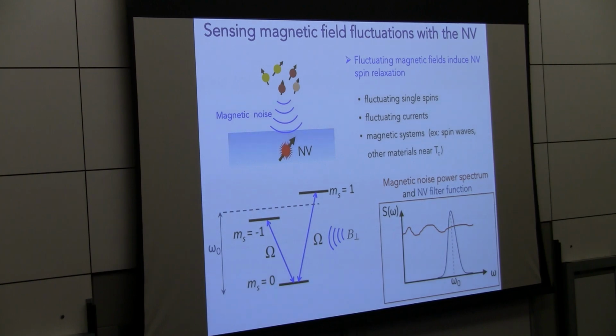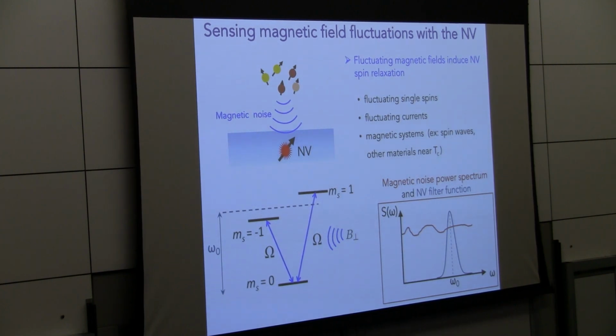Okay, so I mentioned one of my theses here is that the NV is a very versatile sensor, and in addition to DC fields, it can sense fluctuating fields. Another way that we can detect fluctuating fields is outlined here. In DC magnetic field sensing, effectively what one is sensing is some phase evolution of a quantum state, a coherent phase evolution that's limited by the T2 star. But in another sensing modality, if one monitors the T1 time, the relaxation time of a two-level system, that relaxation time is sensitive to magnetic field fluctuations that have a frequency spectrum exactly at that splitting.